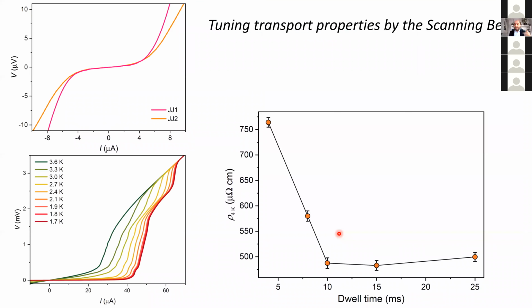Moving on. What I'm showing you here is the resistivity of the materials that we use for the weak link as a function of dwell time, which you can think of as the scanning speed of the electron beam. You see that there is quite a large range over which we can vary and tune the resistivity of this weak link material. And the lower the resistivity, of course, the higher the critical current. So with 10 milliseconds, we have 40 microamp critical current. But if you go for 4 millisecond dwell time, which is more resistive, we have a smaller critical current. And so it gives you a parameter that you could use for tuning the Josephson transport, how much supercurrent can go through your Josephson junction.